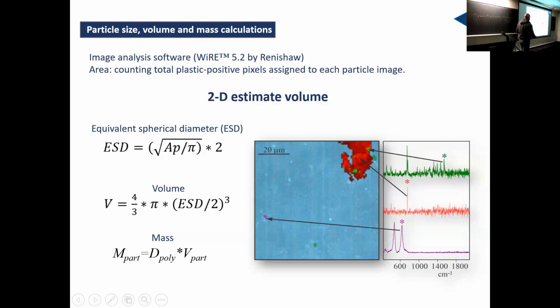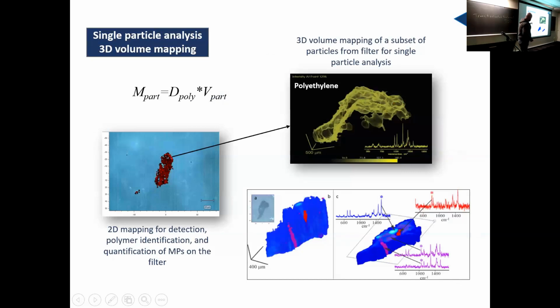So knowing the volume, and because the Raman tells me the identity of the polymer, I can now calculate the mass of the particles, which is the density of the polymer, which is something that you can look up on the internet, multiplied by the volume of the particles. Now I have everything that I need. I have number of particles, I have area, I have volume, and I have the masses of those particles per liter of water in my sample. But not only that, I can do 3D imaging, 3D mapping of those particles if I'm interested in doing that.